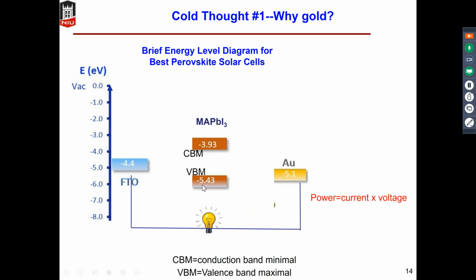Its valence band resides at about 5.43 electron volts below the vacuum level. So when the incident photon strikes on the material, it generates the electron and holes, right? And for the purpose of photovoltaics, we want the electron to go to the anode side, which is the transparent FTO electrode. That is to say, we have to block the electron transport to the other side. So we have to have some electron blocking layer.